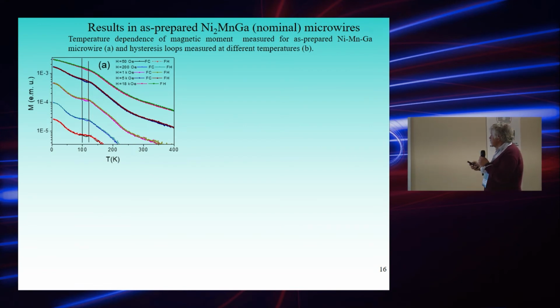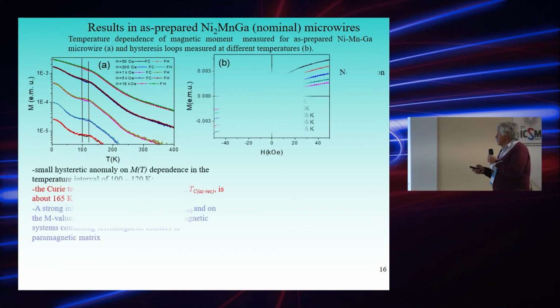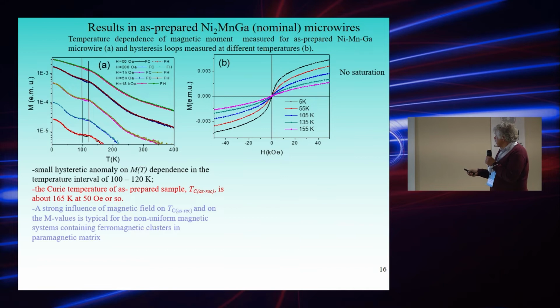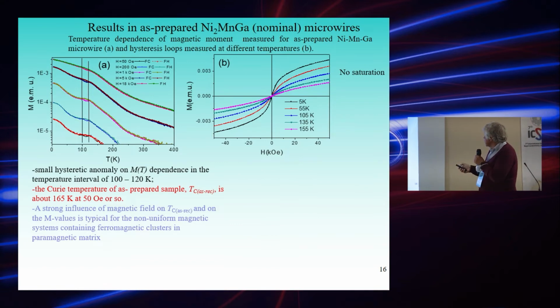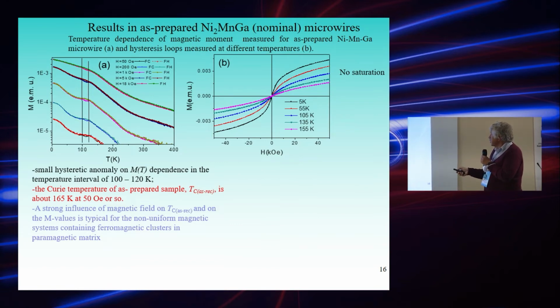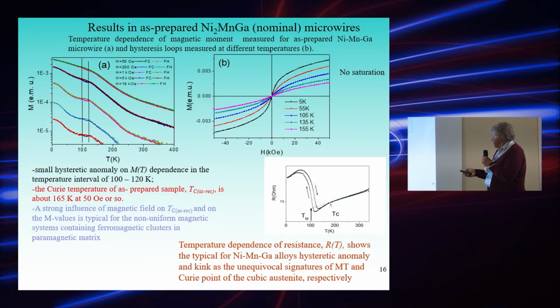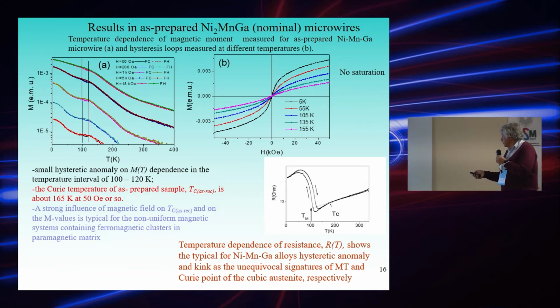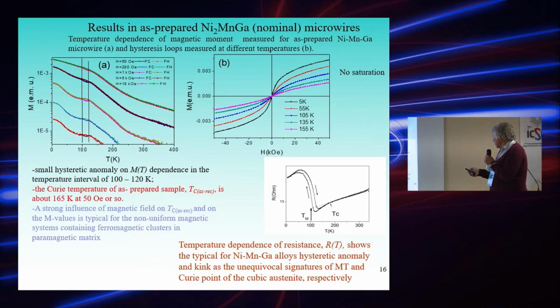In fact, I just prepared several recent results. Usually as-prepared samples have features like not showing saturation even at low temperatures, which is somehow unusual. But in one of the results which I present here, we found some kind of small hysteresis on magnetization curves, heating and cooling. Then we tried to measure electrical resistance versus temperature, and we found a typical anomaly at a temperature of about 100 degrees, which could be a signature of a magnetic transition. However, it's a little bit strange because we didn't observe evidence of such a transition, only a slight hysteresis on the magnetization curve.